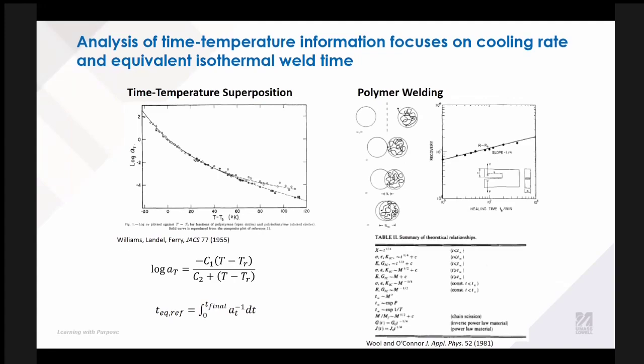So then we can take this time-temperature information and use time-temperature superposition to calculate an equivalent time at a reference temperature, which we take to be the glass transition temperature. Time-temperature superposition generally states that phenomena that occur over long time scales at low temperatures are equivalent to phenomena that happen at higher temperatures over shorter time scales. For every amount of time we can calculate a shift factor, then integrate all of those shift factors across time in our system, and calculate an equivalent weld time. The equation we're using here is the Williams-Landel-Ferry equation, and it works well for amorphous polymers. We're working with ABS here, so this is an appropriate treatment.